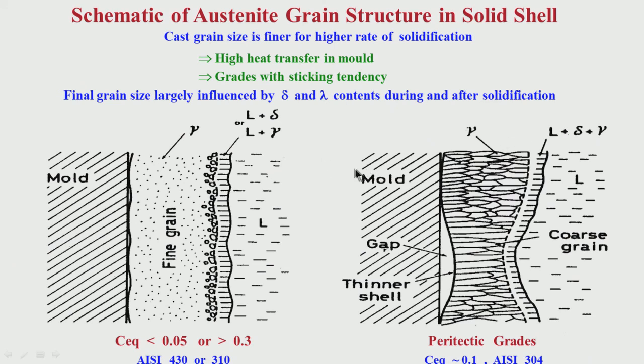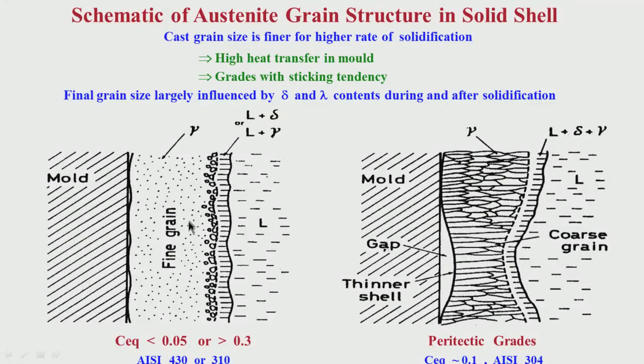So, we have to keep in mind, depending on the solidification characteristic or type of solidification behavior, whether it is sticking type or depression type, we can design the casting parameters accordingly to get better surface quality, better internal quality of cast structure. Similarly, as I have told you, for this type of grades, normally you have to use relatively less secondary cooling intensity. For such grades, we do not want a high rate of heat transfer, not only in the mold, even below the mold. So, the secondary cooling also is relatively less. So, depending on the grades, we have to design the casting parameters accordingly. Thank you very much.